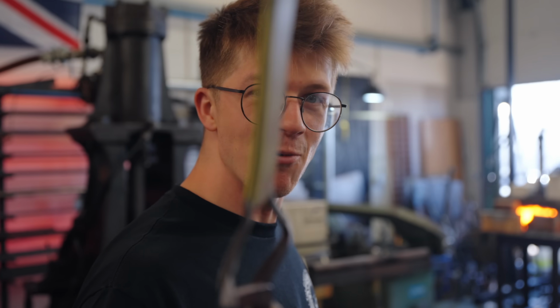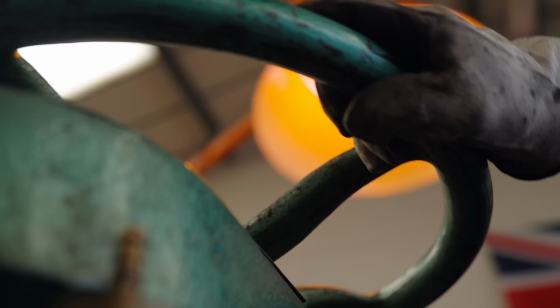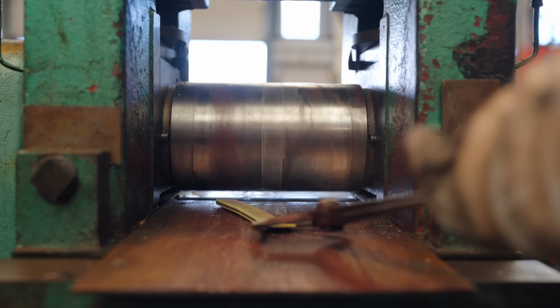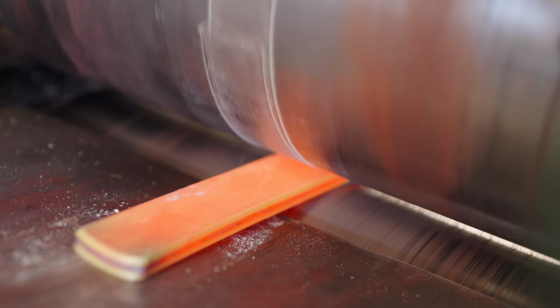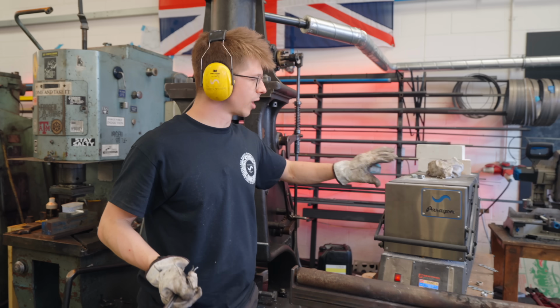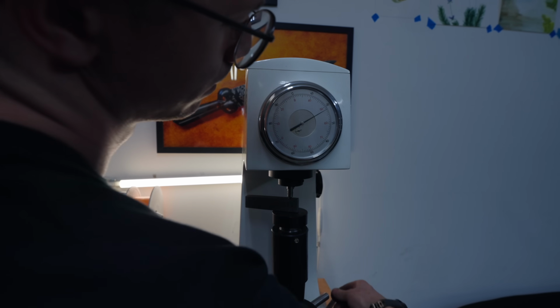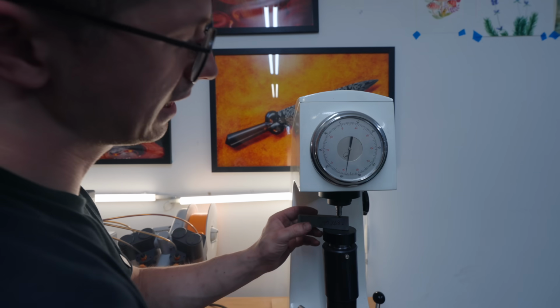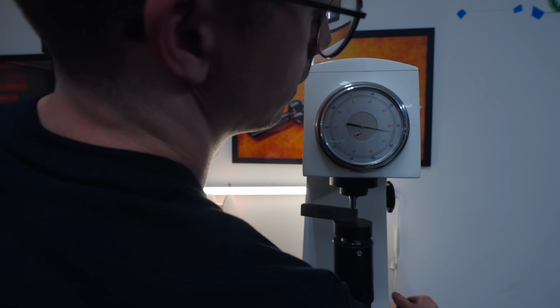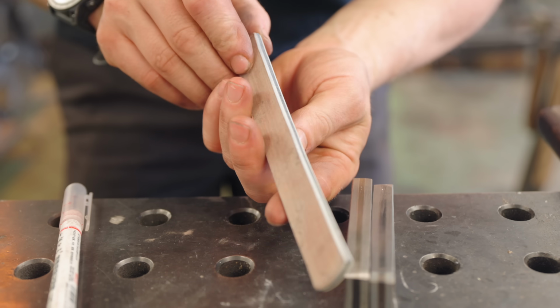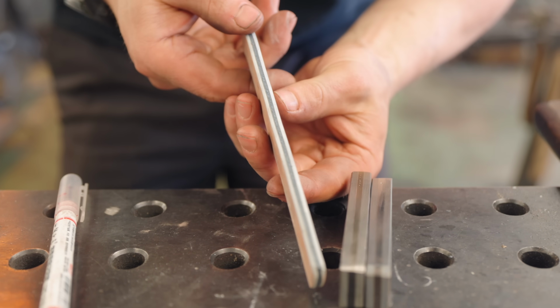It looks like it's still in one piece. Oh! Looking good. Okay, go back up to temperature, then we're gonna let it air cool. Oil hardened after tempering, 57, 58. Air cooled sample, 32 Rockwell, definitely softer. Our rolled sample is looking quite promising.